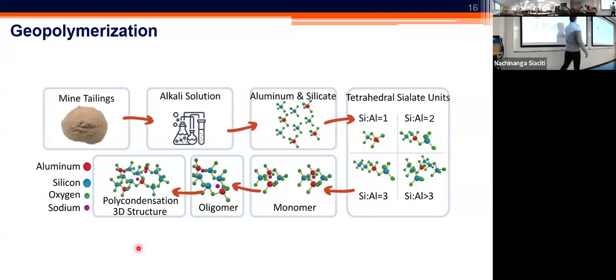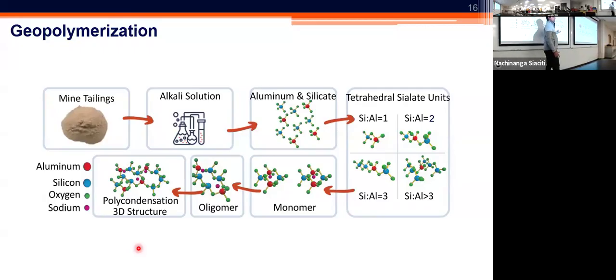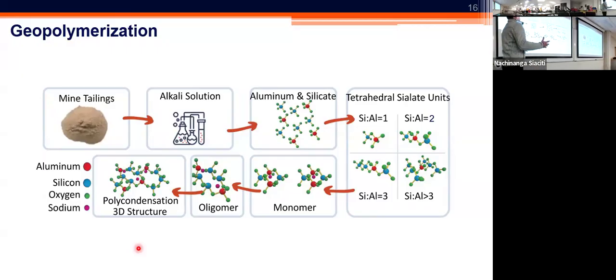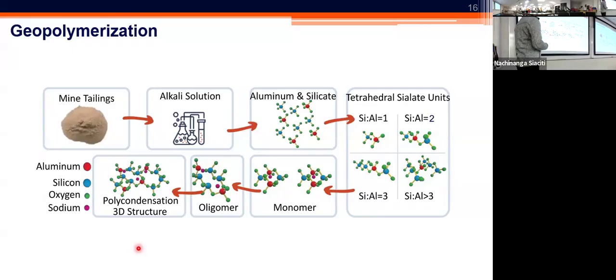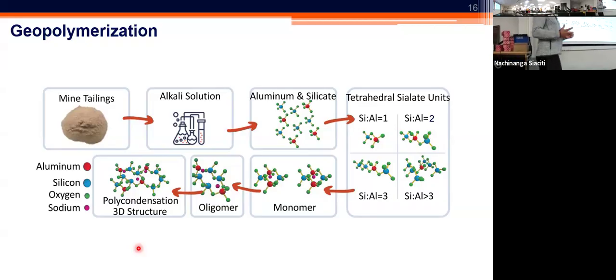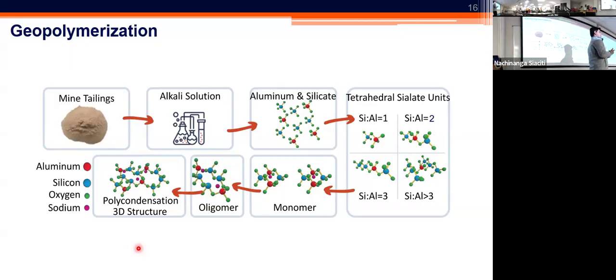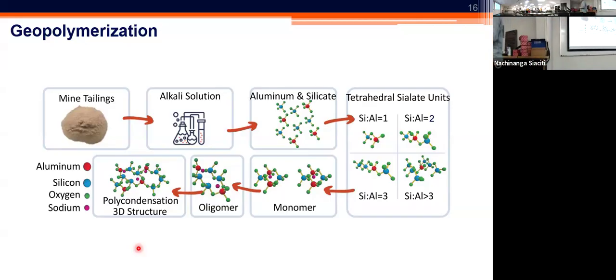We usually like to have a silicon to aluminum ratio of 3 and higher for the production of geopolymers. There is a trend that when you achieve those levels, the material not only will be stronger, but also more durable. So we usually favor that specific ratio. These materials connect to each other in terms of the silicon particles, and also have some aluminum bonded to them, and then they form monomers, connect further together, form oligomers, and then these oligomers go through the polycondensation reaction to generally form the basic backbone and structure of the polymers that would be able to bond not only the more reactive species, but also the unreactive species. In other words, you build on the reactivity of some small content of your tailings, but then produce cementation for the unreactive content in your material as well.